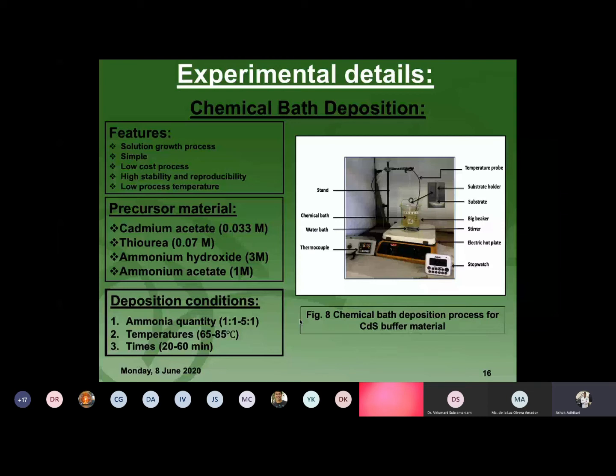You can see from figure 8 the chemical bath deposition setup we developed in our lab, which needs simple things like a stopwatch, electric hot plate, beaker, substrate holder, thermocouple, and precursor solution material. For the CdS deposition, the substrate is mounted vertically with the help of the substrate holder.